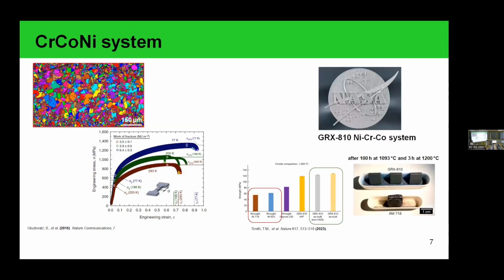And based on this system, this year NASA presented a new alloy for high temperature applications. They prepared the pre-alloyed powder, printed it using 3D printers, and compared the oxidation resistant properties with the nickel alloys. It demonstrates better oxidation resistant properties, and even the tensile properties at elevated temperatures are higher in comparison with the nickel superalloys.